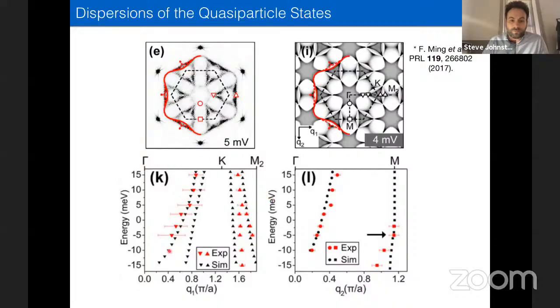So we basically argue that this is really evidence that this quasi-particle peak we're seeing emerge as a function of doping is really a dispersive state. And that's really consistent with the notion that it's the quasi-particle state that forms once you dope the Mott insulator. And it's not an impurity state. It's not coming from boron impurity states that show up inside the gap, or something happening to an impurity state in the tin monolayer, for example. So we argue that this was really the evidence that the system could be doped and it behaved like a doped Mott insulator in the end, because we have the spectral weight transfer plus the dispersions.